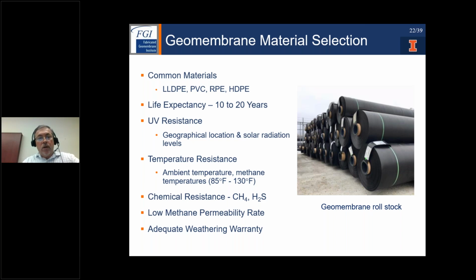Temperature resistance is also very important. Looking again at the regional ambient temperatures, but more specifically at the methane temperatures. Certain phases of the digestion can see temperatures ranging from 85 degrees Fahrenheit to 130 degrees Fahrenheit. And at 130 degrees Fahrenheit, those are high long-term temperatures for the geomembrane to withstand, and it's very challenging. Chemical resistance is also very important, certainly making sure we have a geomembrane with noted chemical resistance to methane and the H2S gas.